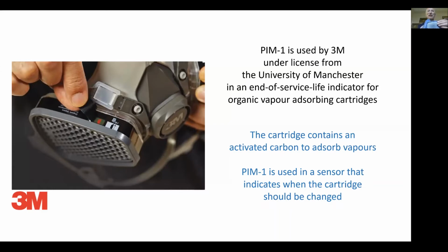And the cartridges actually contain something called an activated carbon. That's a very useful and relatively cheap adsorbent. But the difference with these particular cartridges is that there's a little window on the side. As that cartridge is used up, because it doesn't last forever and you need to change those cartridges at intervals, a little red bar moves across that window. And that tells you how much of that cartridge has been used and gives you an idea of when you need to change the cartridge. And our polymer is the key thing that makes that little sensor work. So that's a way in which that polymer is being used right now and is available commercially.